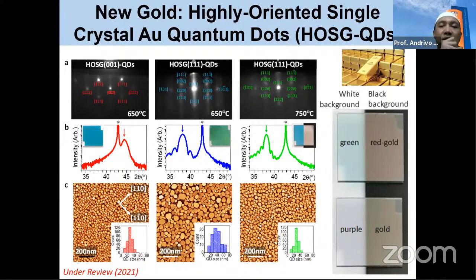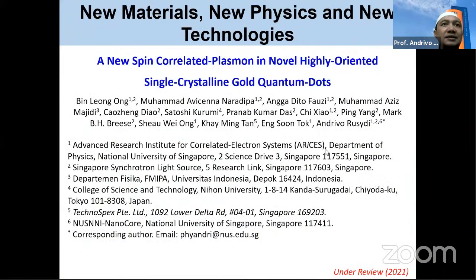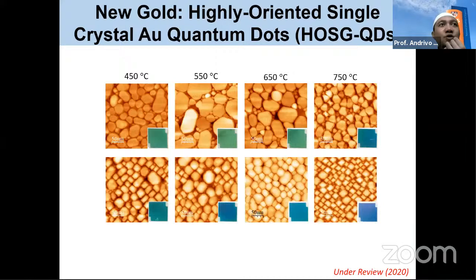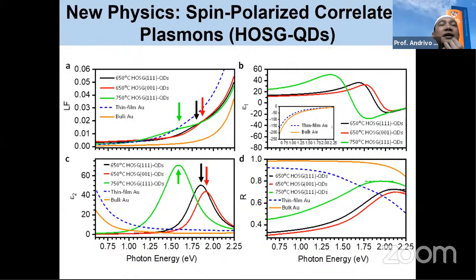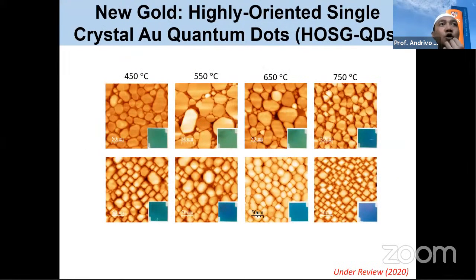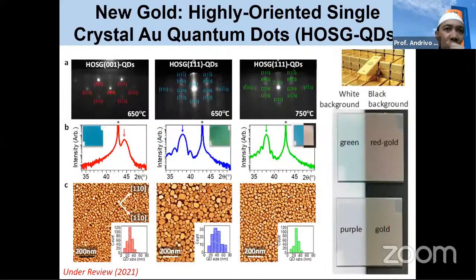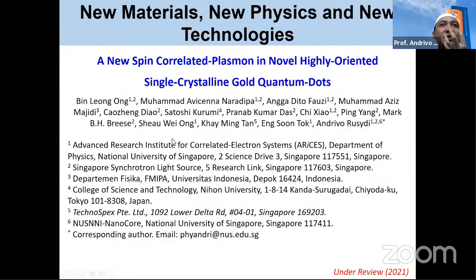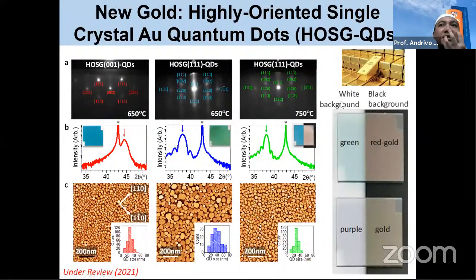And what is really important is that along this line, we are also working closely with industry. This is TechnoSpex, with industry in Singapore, to make use of this gold, to make use of the spin-correlated plasmon, the new phenomenon, to detect a biological system. So just go back here a bit. If you look here, the color of the gold, which was just yellow, depends very much on how we grow the material. It's no longer just yellow, but a different type of color, and they're all transparent.